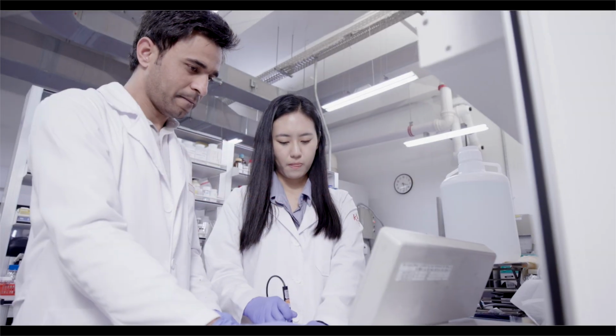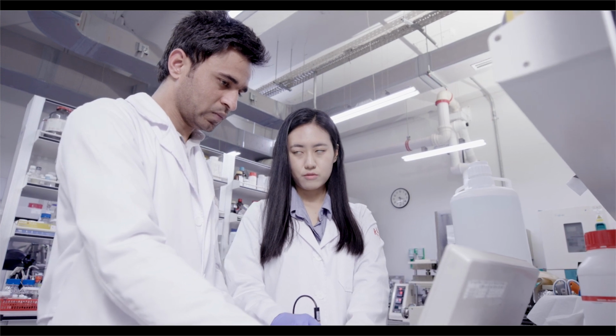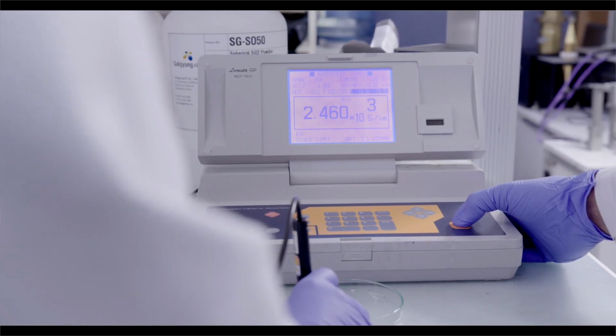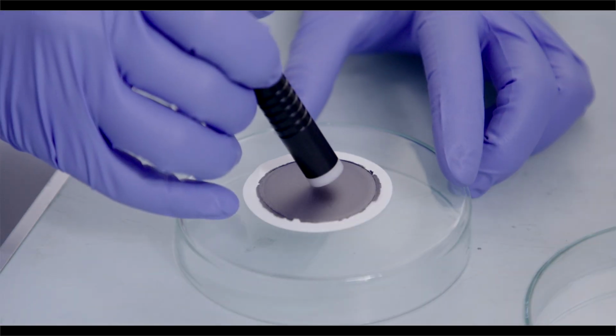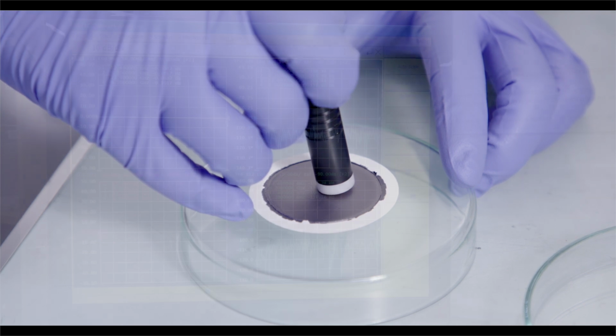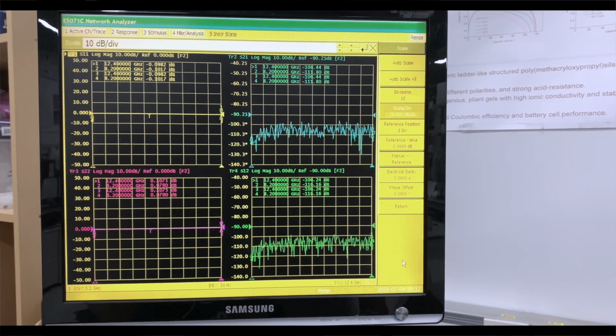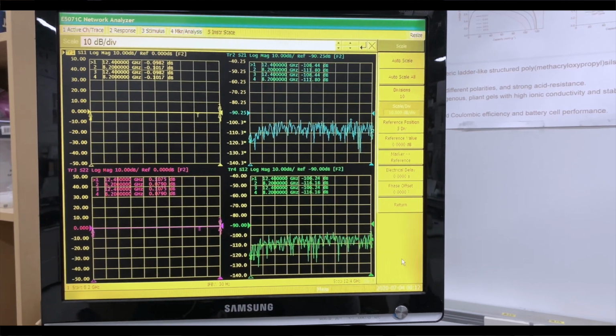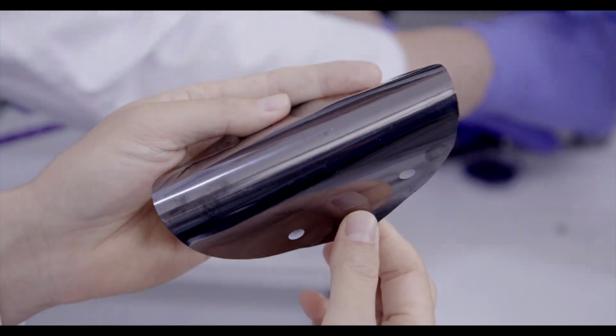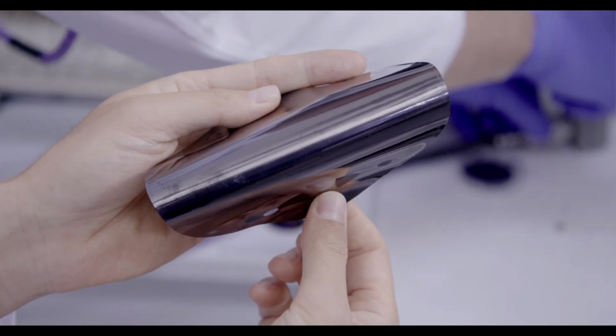The extraordinary EMI shielding performance is due to the anomalously strong absorption property of the layered Ti3CN films. The Ti3CN films have a compacted laminate structure, which converts into a metamaterial-like porous laminate structure after mild heat treatment. Incident electromagnetic waves are strongly absorbed in this porous structure, not only by strong internal reflections from multiple interfaces, but also by the metastructure effect. The designed porous structure with improved effective permeability and permittivity strongly attenuates the energy of electromagnetic waves by ohmic, eddy current, and polarization losses. Therefore, the metamaterial-like structure gave 116 decibels of EMI shielding effectiveness at a 40 micrometer thickness, which is the highest value ever reported for a synthetic material.